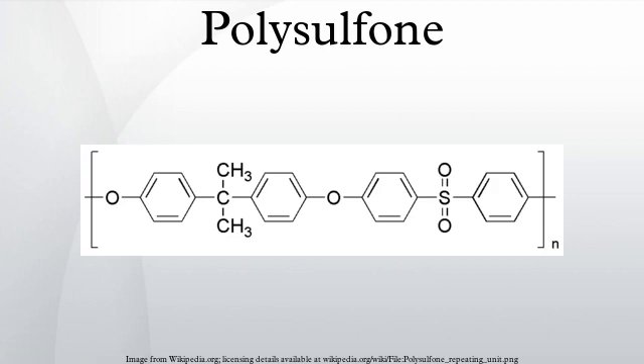Polysulfon is often used as a copolymer. Recently, sulfonated polyethersulfons (SPES) have been studied as a promising material candidate among aromatic hydrocarbon-based polymers for highly durable proton exchange membranes in fuel cells. The biggest challenge for SPES application in fuel cells is improving chemical durability. Under oxidative environments, SPES can undergo sulfonic group detachment and main chain scission, with the latter being more dominant. Midpoint scission and unzip mechanisms have been proposed as the degradation mechanism depending on the strength of the polymer backbone.